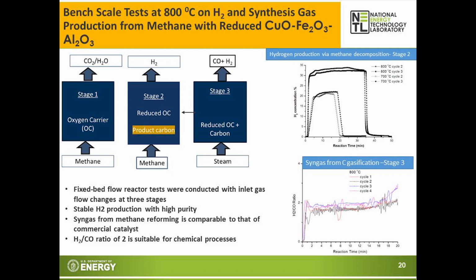These are the hydrogen production data. During stage 2, you can see we get a very high conversion of methane to hydrogen at 800 degrees C. It's higher than that at 700 degrees C. And during cyclic operation, we get very stable performance as well.